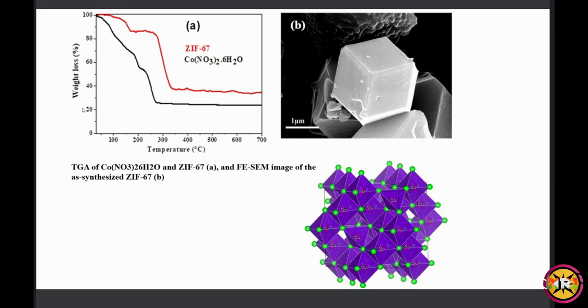in the tetrahedral hole, and cobalt 3+ is sitting in the octahedral hole, and oxygen is sitting in the lattice site. So basically, I have synthesized Co3O4 by three different methods: via solution combustion synthesis, via solid state synthesis, and via calcination of zeolitic imidazolate framework, that is a subgroup of MOF.